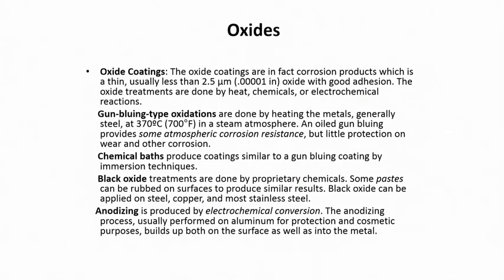Then gun bluing type oxidations are done by hot heating the metals, usually steel, at 370 degrees Celsius in a steam environment. This gun bluing type oxidation gives rise to a very thin oxide layer, blue in color. Then a chemical bath produces a coating similar to gun bluing coating by immersion techniques.